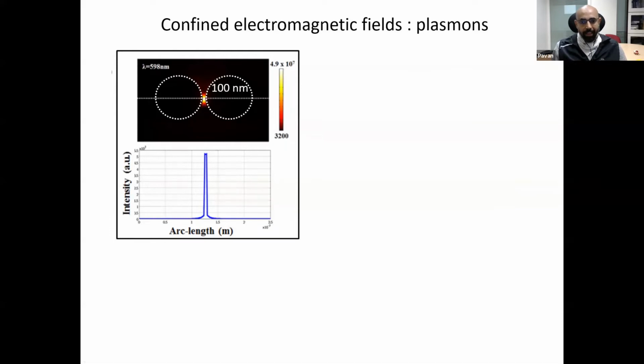There is no final say on what really is happening because, for example, if you put a fluorescent molecule here, they may first of all quench their fluorescence. But if they are placed in a very specific way in this hotspot, you might end up getting some very interesting enhancement of the radiative decays from the molecule.